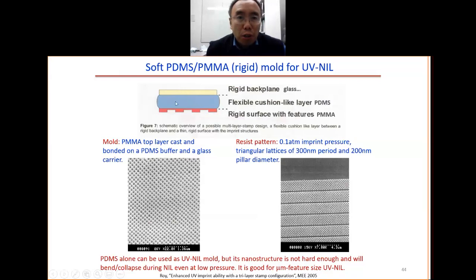So this example gives you the soft PDMS mold. Here we have the rigid backplane, and we have this flexible PDMS. This is the flexible elastomer. On the top, we have this also rigid PMMA. We know that for the PDMS, the Young's modulus is a few megapascal. For the PMMA, it's a gigapascal, 10 to the power 9 pascal. So the Young's modulus is much higher than PDMS. So you can have very high resolution features.